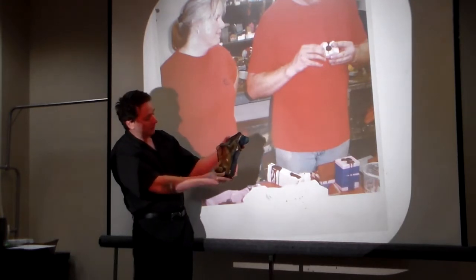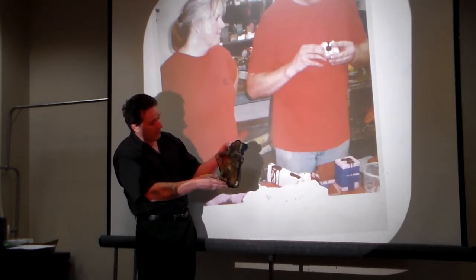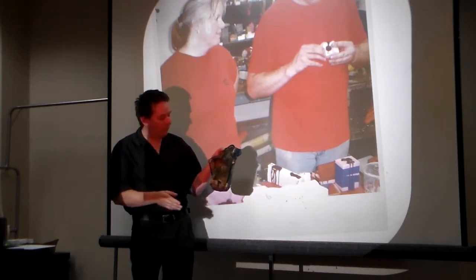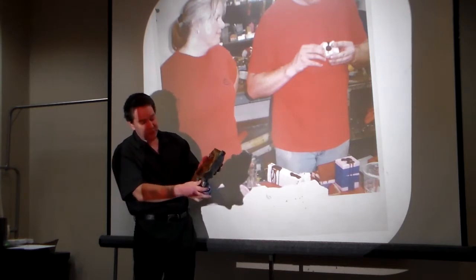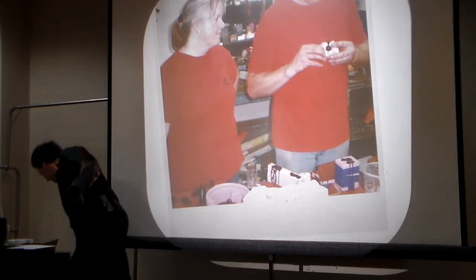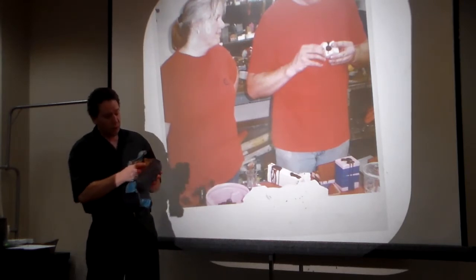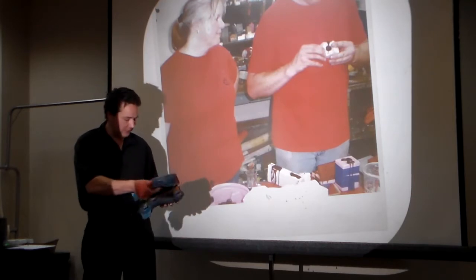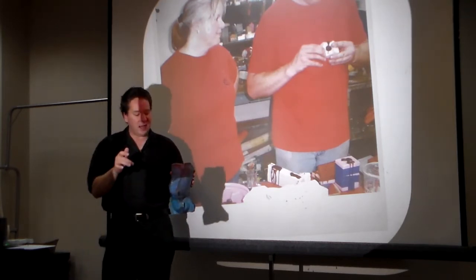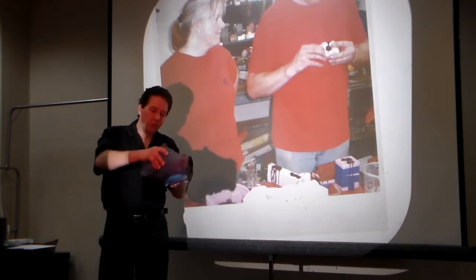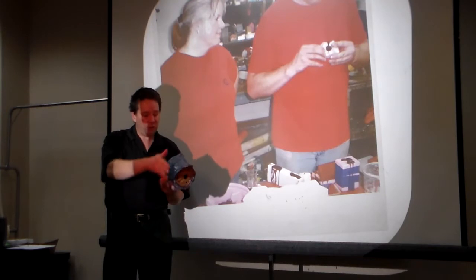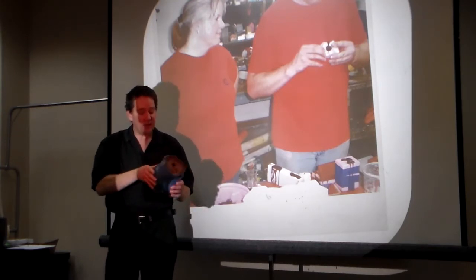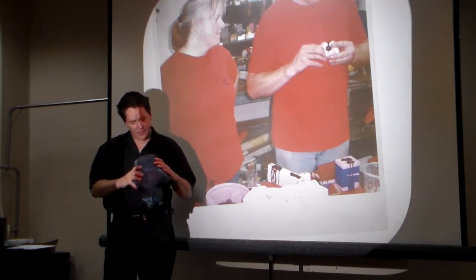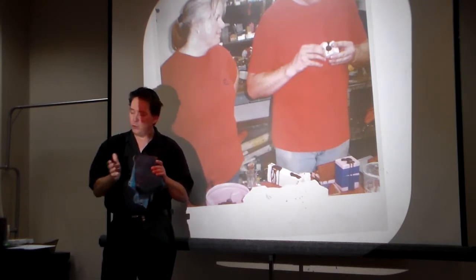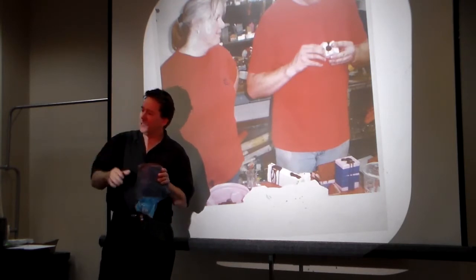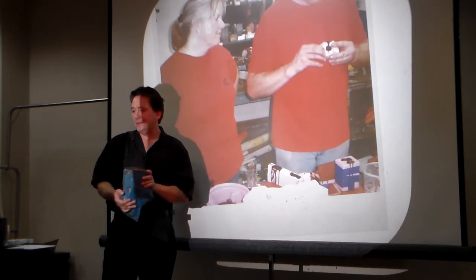This is a little bust of Aeneas, about 6 inches tall, and this is pretty thick. We don't want to cast it completely in wax. So we've got a hole here, and after the two halves of this mold are clamped together, here we have rubber inside of a shell, and I'll get a little bit more detail into that later. We'll fill this up with the hot wax, and we'll pour it out this way. And I'll rotate the mold slowly to get a uniform shell of wax around the inside. Now that shell is only going to be a 1/16 of an inch thick, and we want it a 1/4 of an inch thick. So after this cools for half an hour, I'll go back and I'll pour a second time, pour it out a second time, 5 times all together.